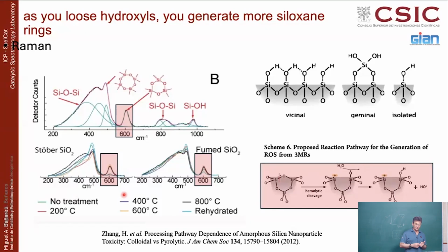I was telling you the other day, silica has very few hydroxyl groups. Typically, when you are talking about this surface, silica has about a hydroxyl per square nanometer, the fumed silica. And other oxides, other supports have up to 6, 7, 8 hydroxyl groups per square nanometer. So they have a much better dispersion capacity. But silica can be prepared by hydrothermal synthesis, and it will be highly hydroxylated, it will be more like that, or can be like fumed silica with very few hydroxyls.